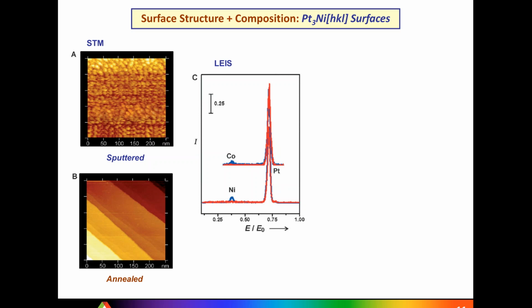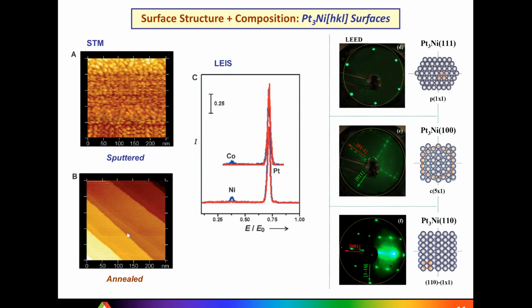But the point and message here is that, in order to obtain a clean surface in vacuum, one needs to apply so-called sputtering in order to get rid of any impurities, and this is how the morphology of the sputtered surface looks like. However, after annealing, that surface gets very smooth, with nicely ordered atomic structures in case of single crystals. But what was also interesting is that the surface composition of those annealed alloy surfaces turned out to be pure platinum, and even after all of those experiments in vacuum, we termed that surface platinum skin. So in addition to distinct surface structure, which is confirmed from LEED studies, we could assign that surface composition was pure platinum.